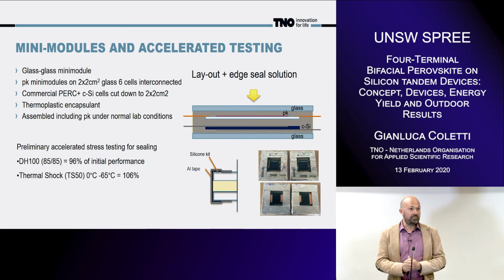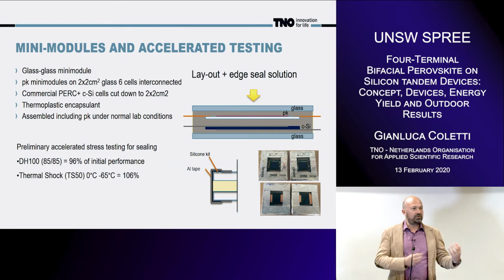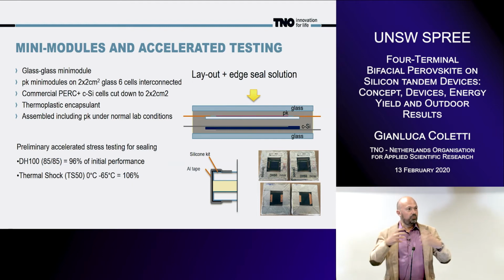Then we did the thermal shock, and this is more to stress the interconnection, the metallization. And here we have a 106% initial performance, because the annealing itself did something good in the perovskite. But then we combine now the thermal cycle with the damp heat, which is the worst condition.